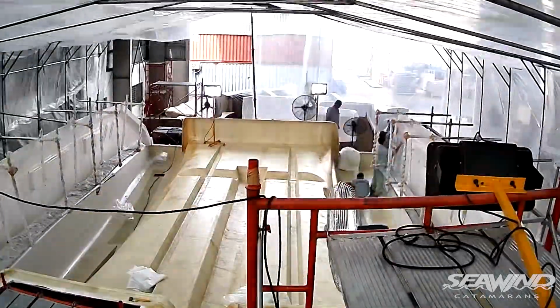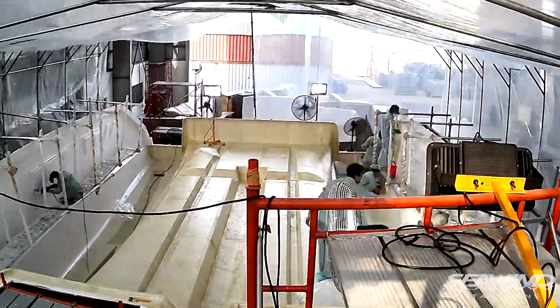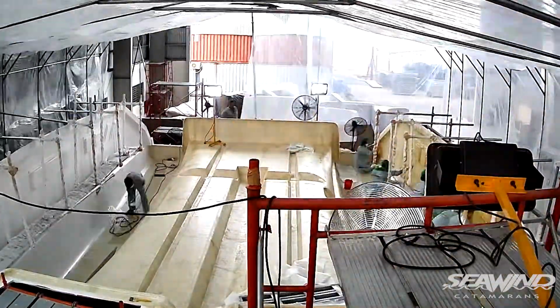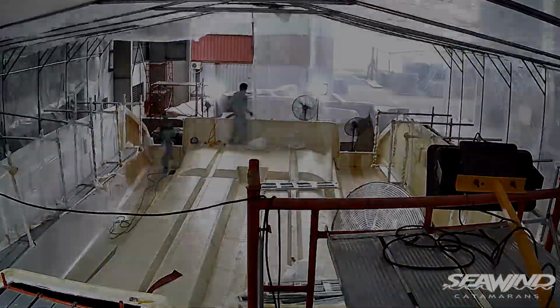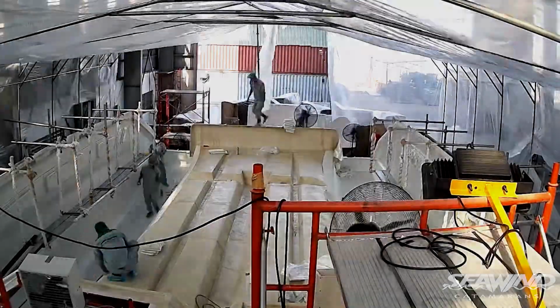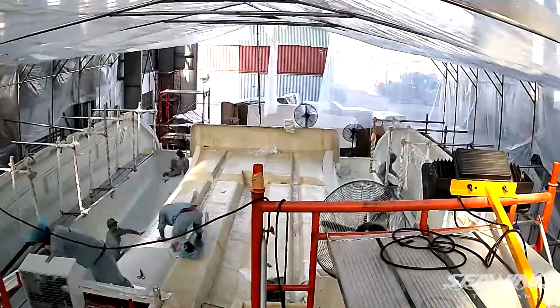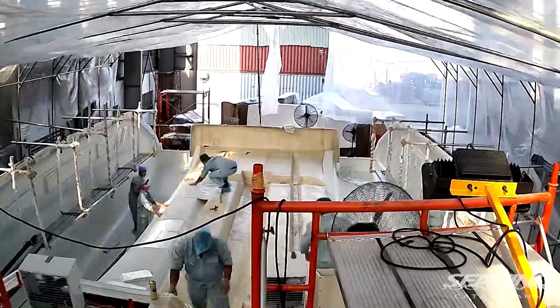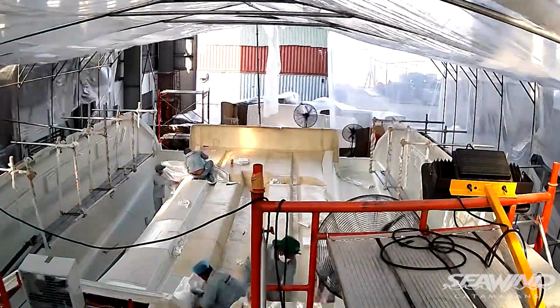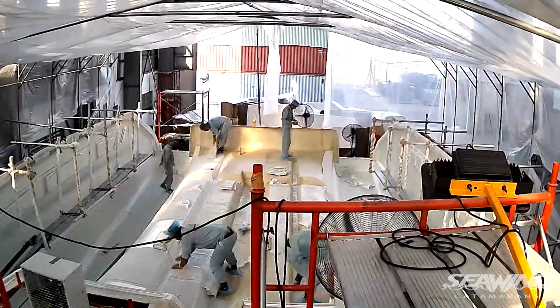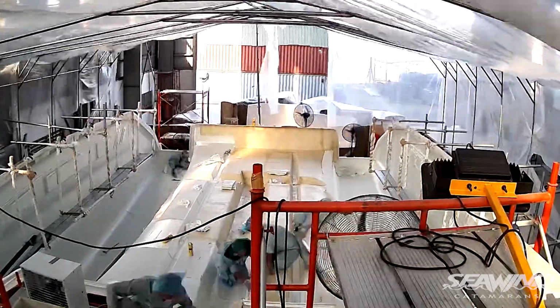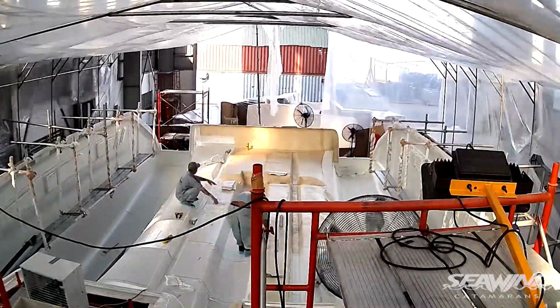Our first job, like most of our glass boats, is to gel coat and tie layer the mould, which we do with a high quality marine gel coat and a vinyl ester resin, which gives us a hull with full protection from osmosis. Once this layer has cured and been sanded, we can start loading the glass fibre to make the strong composite laminate. These are applied as a dry fibre in a uniform layer by following our detailed engineering drawings and are temporarily held in place by spray adhesive.